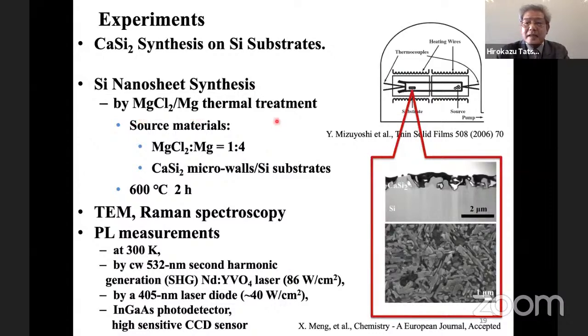For the growth process, a substrate with calcium silicide and magnesium compound is placed in this glass container and put into the vacuum chamber. Then it is thermally annealed at about 600 degrees C for 2 hours. And we characterize using these techniques.